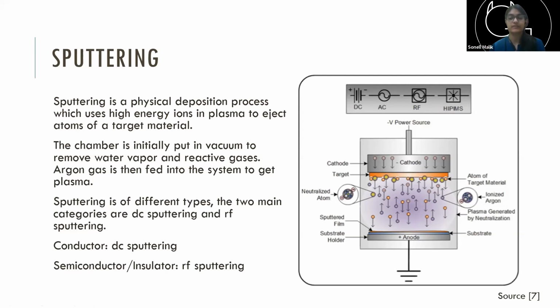Now, because there is a high voltage difference, any free electron initially that is close to your cathode will be accelerated towards the anode. When it reaches a high enough energy, it will collide with some argon atom in the space itself. That ionizes that argon atom and leads to expulsion of another electron. As electrons keep hitting and the number of electrons keeps increasing, it forms a cascade, and you have essentially a plasma, because electrons keep hitting other argon atoms, electrons keep getting ejected, and also some electrons recombine. All of you know that plasma, like you see in tube lights, has a visible glow. That visible glow comes from recombination events.